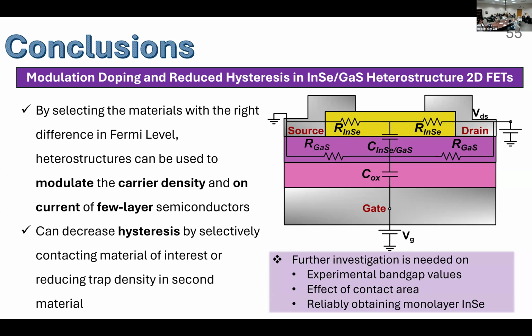So in conclusion, to wrap all of this up and again answer the main question of how do material parameters affect device parameters? In my first project, modulation doping in indium selenide gallium sulfide heterostructures, we saw that by selecting the materials with the right difference in Fermi levels, we can use these heterostructures to modulate the carrier density and the on current of few layered semiconductors. We saw that we can decrease this hysteresis by selectively contacting the material of interest or by reducing the trap density in the second material. The results in this work prompt further investigation on experimental bandgap values.